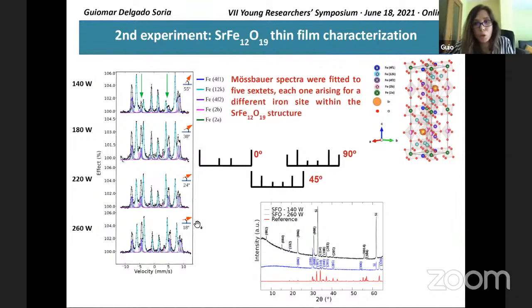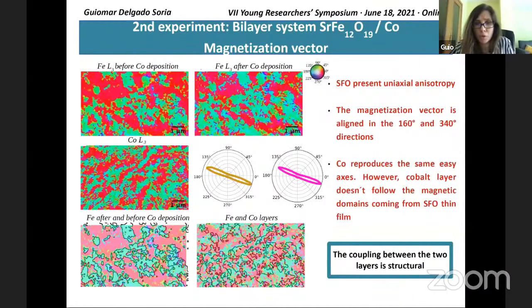This is in good agreement with the result in X-ray diffraction, which determined the easy axis is within the plane. Knowing that the easy axis in the strontium ferrite is in the C plane is in good agreement with what I said, that we have magnetization within the plane. Then we grow a cobalt.